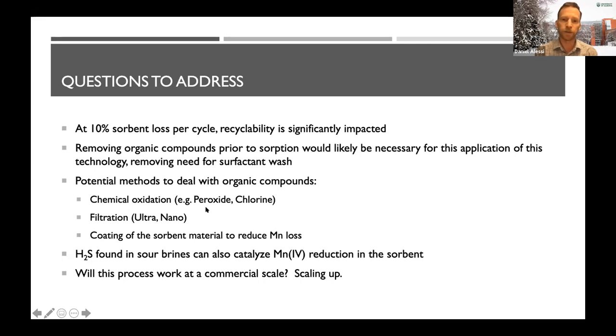I talked actually yesterday with a colleague in Korea about this. It would work quite well to get rid of the organics. Chlorine's another option, although chloride can be a bit difficult to deal with. Filtration: there's some filtration, at least microfiltration, done on site at oil and gas operations. You could think, depending on cost, about implementing ultra or nanofiltration to remove these molecules. We did a bit of nanofiltration. It did help, but it seems like there are very small molecules that make it through the nano-sized membranes and still cause this phenomenon.